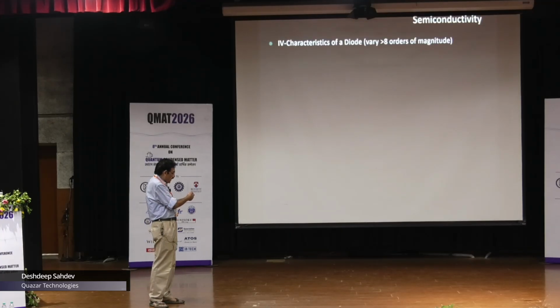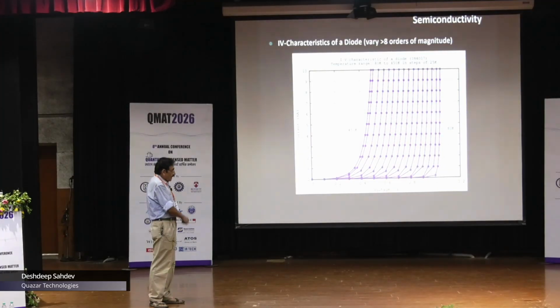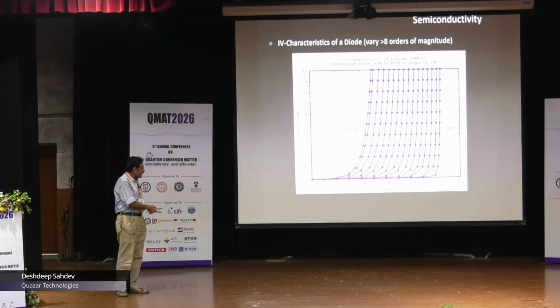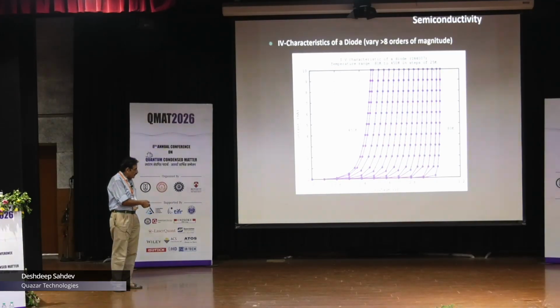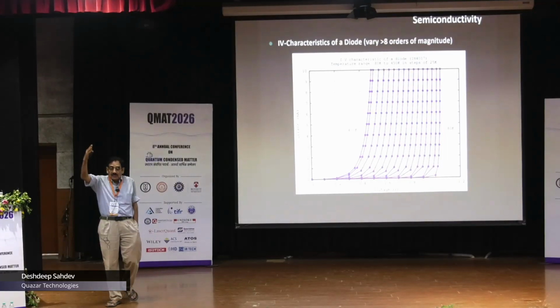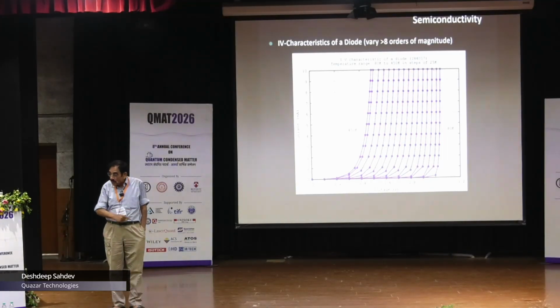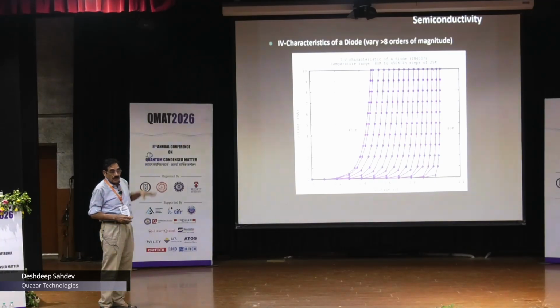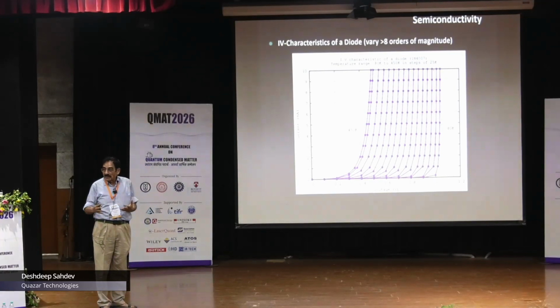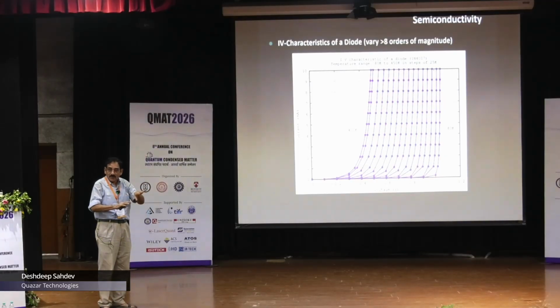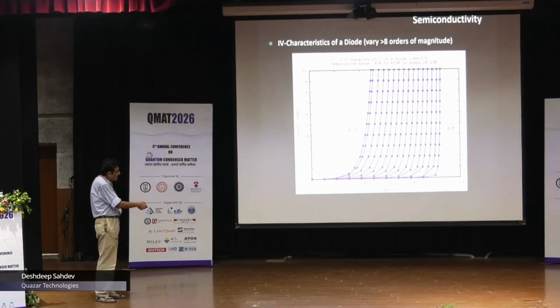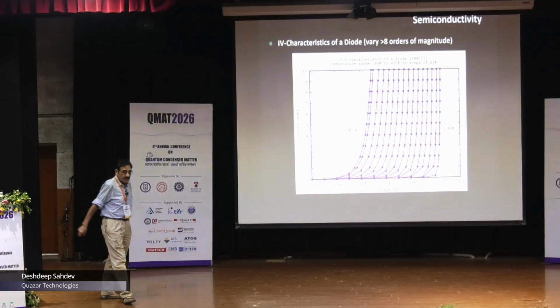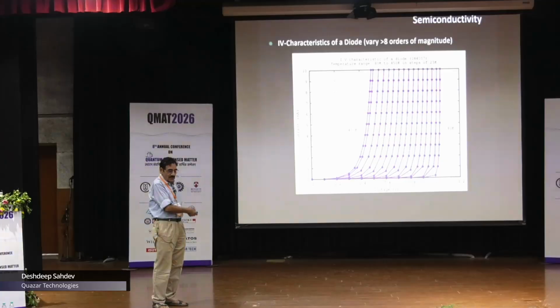Now, a typical thing is getting the current-voltage characteristics of diodes, and you can see that here. If you take the voltage versus current, it's almost completely insulating, and here it's almost completely conducting. So the resistance changes by about 8 or 10 orders of magnitude in just one run. So you have to build in a certain amount of intelligence in order to figure out how to make this measurement. But this is just done automatically. You just program it in and it'll just do it. And this is done from 80 to 450 Kelvin in steps of 25 Kelvin, all right? And you get this whole set of curves out here.